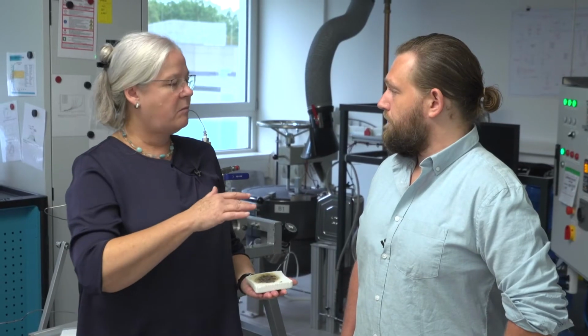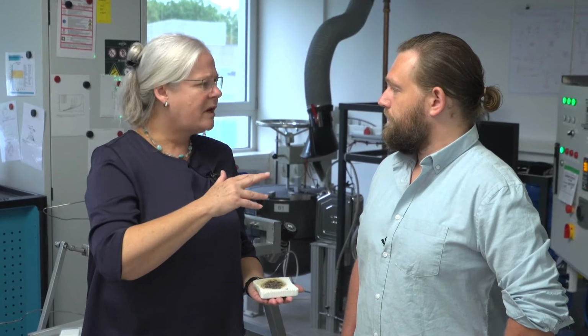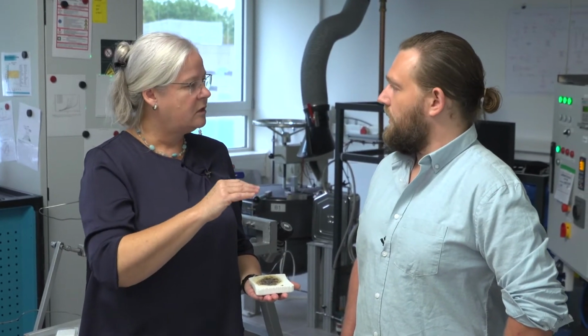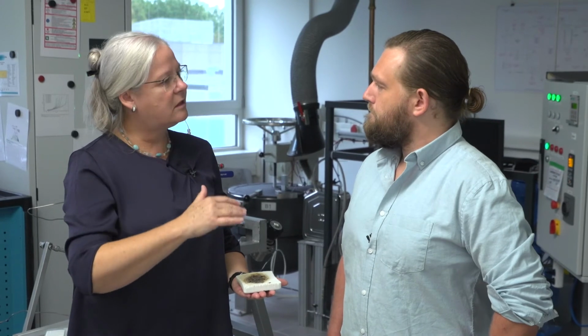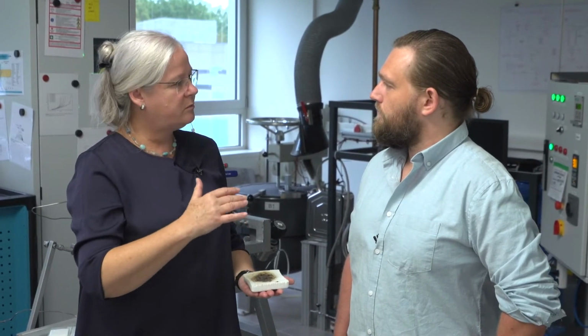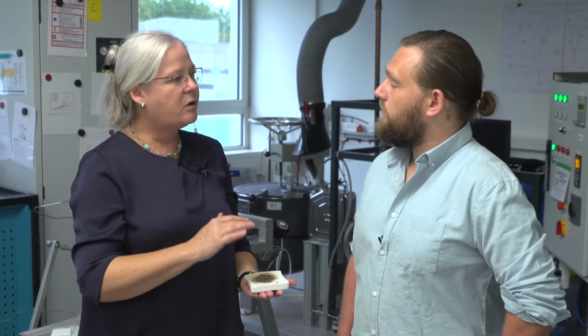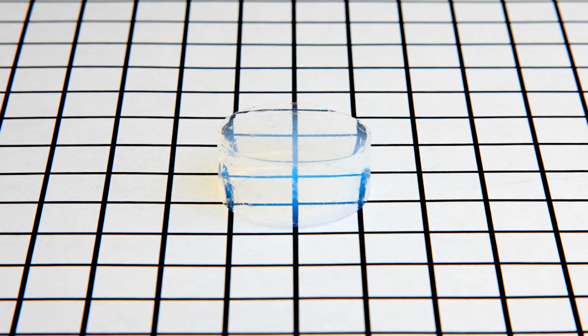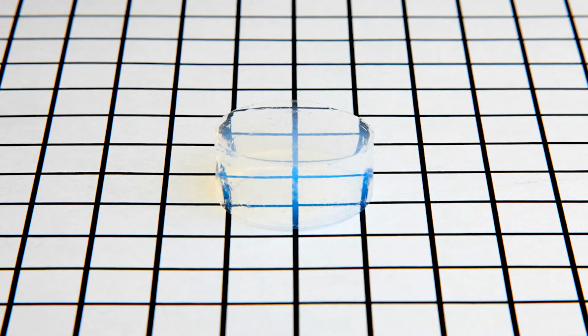boehmite particles, an aluminum material, yeah? Yes, and this leads to a very strong material which is stable up to 850 degrees. Wow. So we see no effect on it. Very cool. And this is very nice because you can use it everywhere where you have hot systems.